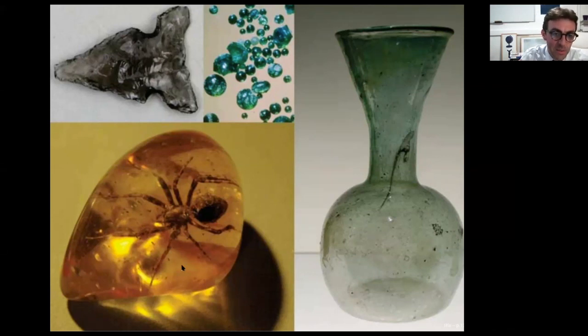Okay, and the one that I will discuss maybe more is the one at the bottom here with the spider inside. So this is an amber glass. It's about 100 million years old. In the last decade, some glass physicists have used a similar type of amber glasses to try and understand how much closer to an ideal glass state they could go using this type of very long aging times. And I'll come back to this later, showing you data. Surprisingly, these experiments seem to show no big differences between 1 day old and 100 million year old amber glasses, which is a bit surprising.